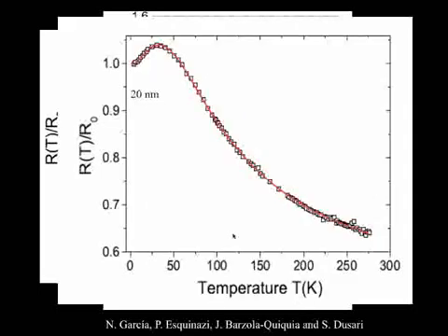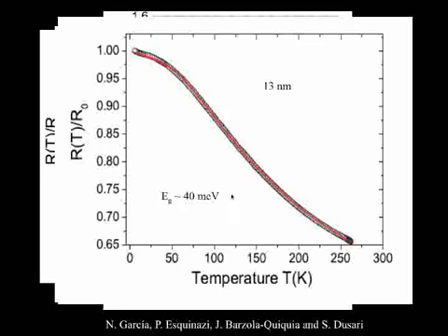Decreasing now the thickness, you see different behaviors, which can be very well fitted by changing the relative contributions. For the thinnest samples, mostly a semiconducting behavior is measured. The saturation at low temperatures is due to the always present free sample surface or interface with the substrate. Important to note is that in all fits we use similar bandgap values, supporting the assumption of the semiconductivity of the graphene layers within the single crystalline region of the graphite sample.